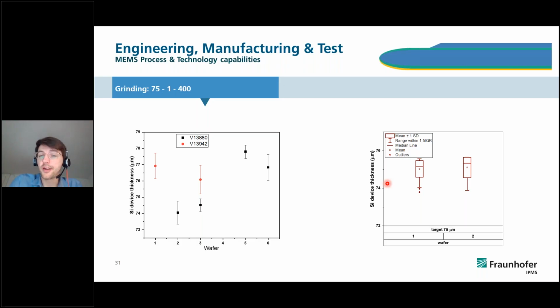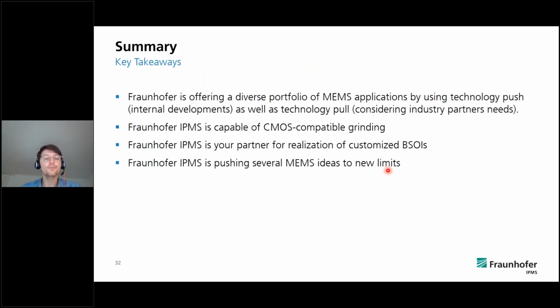Also for the 75, it took us a while to manage this process quite well. As you can see, a wider spread than we would usually try to have. And then after another iteration, we managed to get down to almost 75 over the entire wafer, which was an improvement, but was harder than expected, actually, to be honest with you.